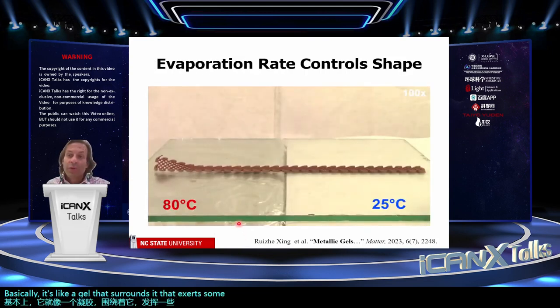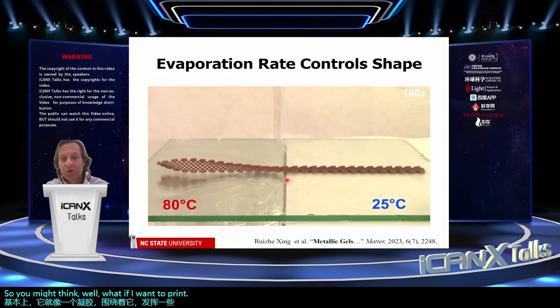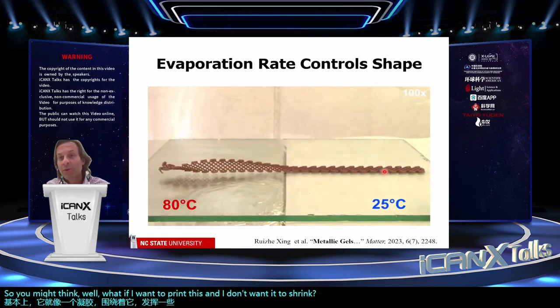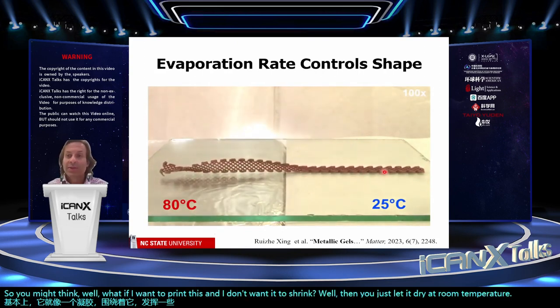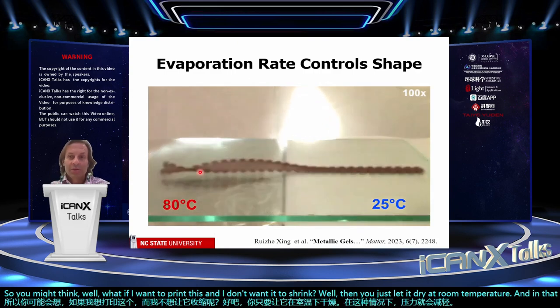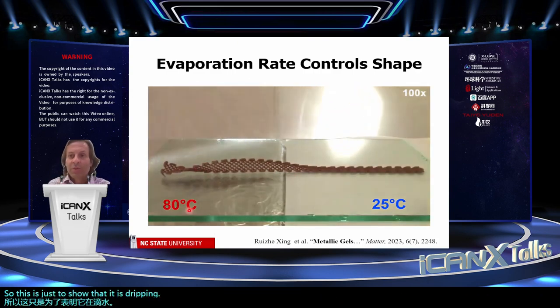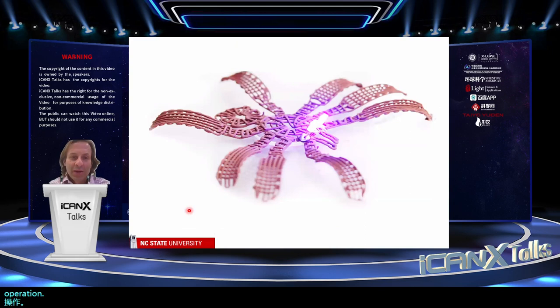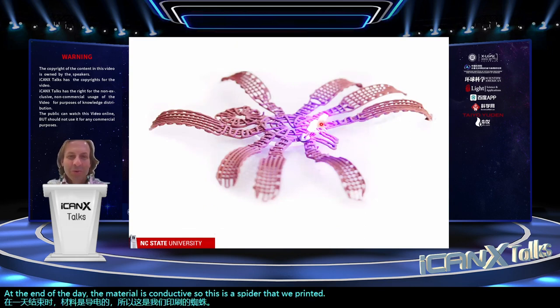So you might think, well, what if I want to print this and I don't want it to shrink? Well, then you just let it dry at room temperature. And in that case, the stress is relaxed and it doesn't change shape. So this is just to show that it is driven by evaporation. At the end of the day, the material is conductive. So this is a spider that we printed. It's really cool with these glow-in-the-dark LED eyes.